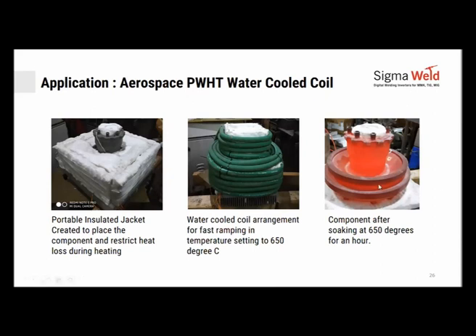As you can see, even the shape, right? Imagine this shape. It's a very difficult shape to preheat. You can see more thickness here, less here. By putting it into an inductive zone, we are able to balance and maintain the heat inside. Once at 650 degrees, it stabilizes for an hour. All parts are equally heated.